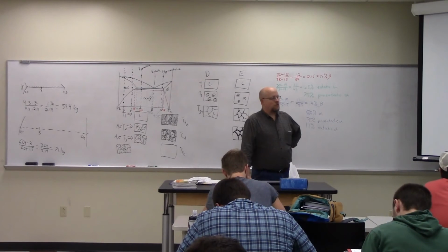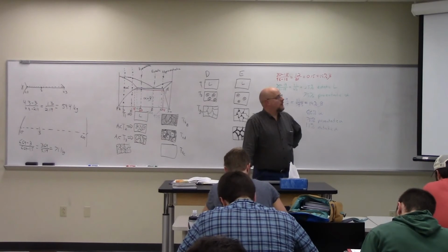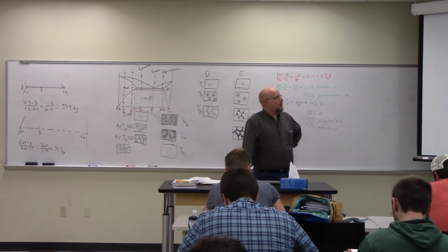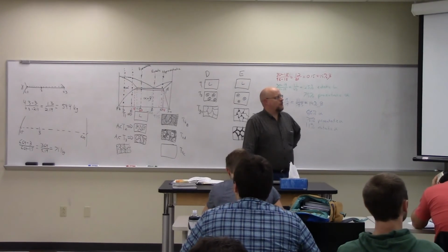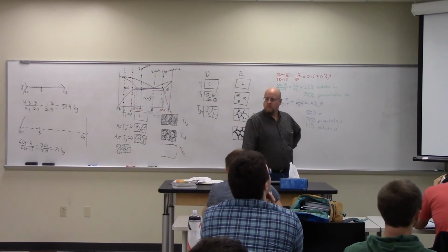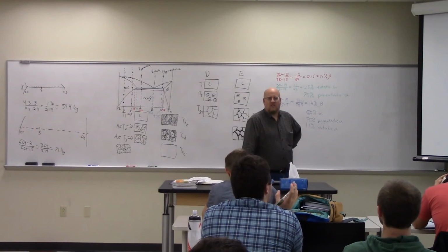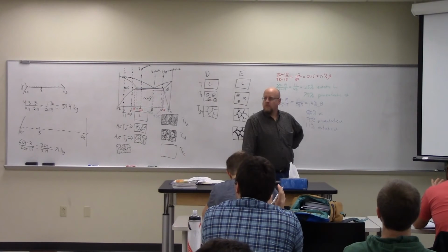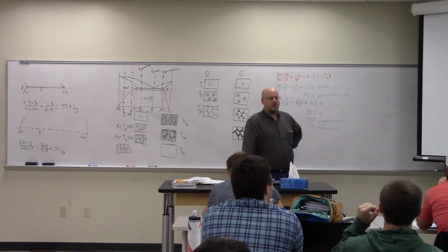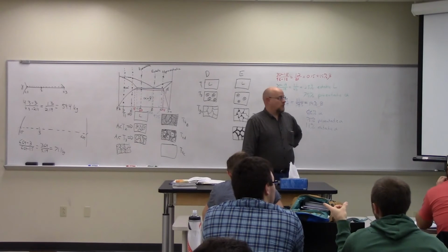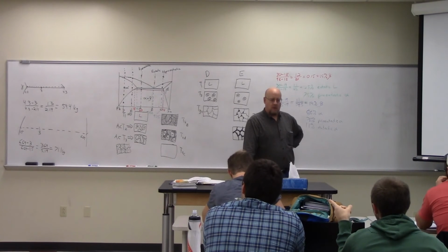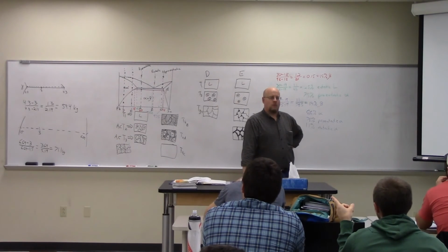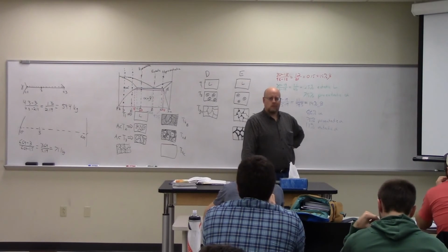I have this chunk of proeutectic material, and then an additional gamma that is formed after the eutectic. That's buried in the lamellar structure. Now, there's been some diffusion of those things, but go ahead. So between that is our total. That is the total gamma, 71.1 kilograms of gamma, and 59.4 kilograms of that is proeutectic. And the rest of it is cementite.